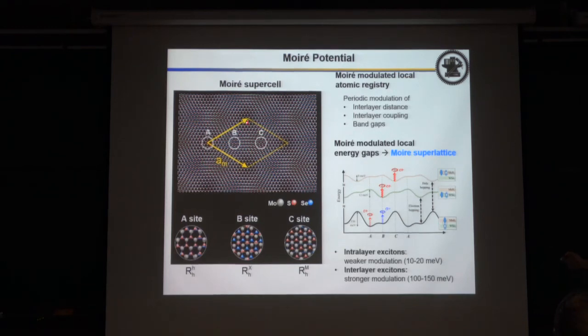So you can see they have some high symmetry points, and they correspond to different local atomic registry. That means you have different registry, and also means you have different interlayer interaction or interlayer coupling. And the interlayer coupling will change the band gap a little bit, so you will form a potential modulation like this.